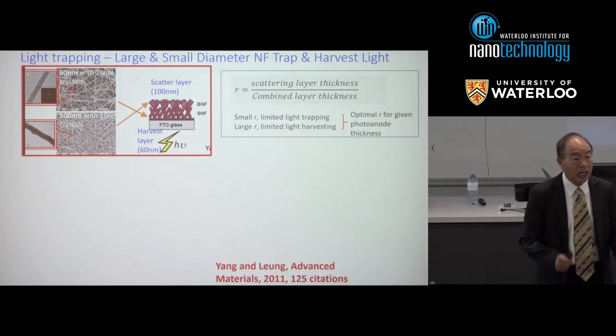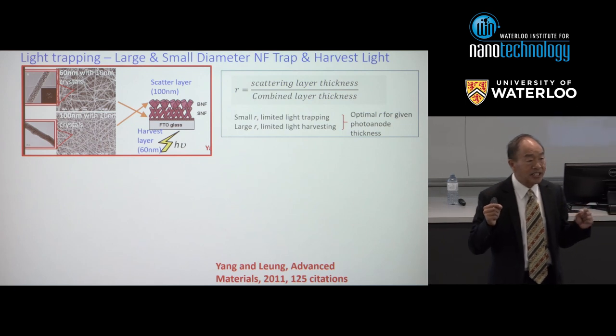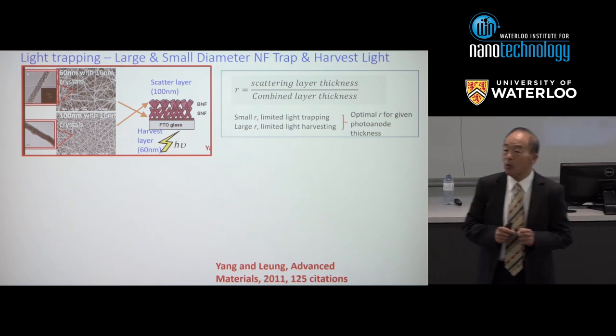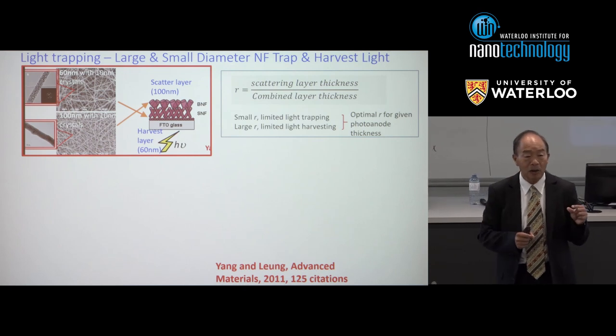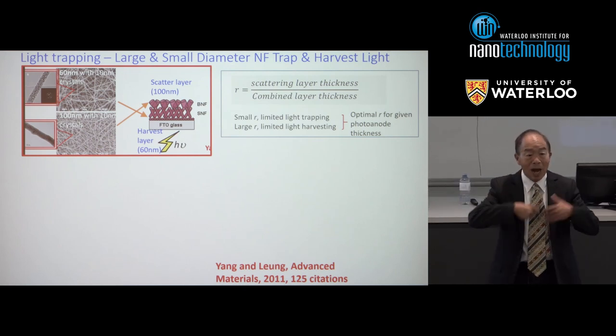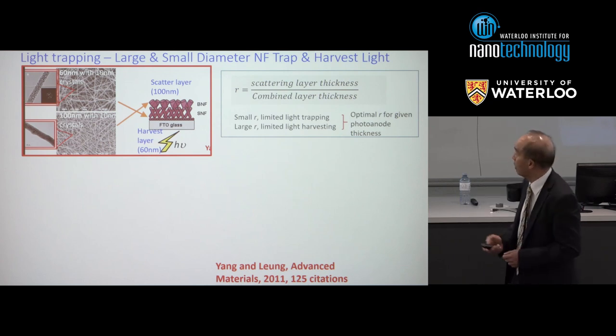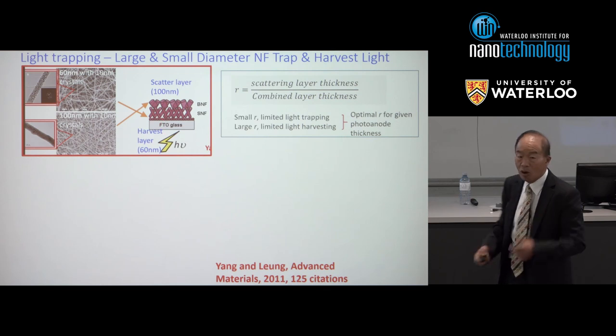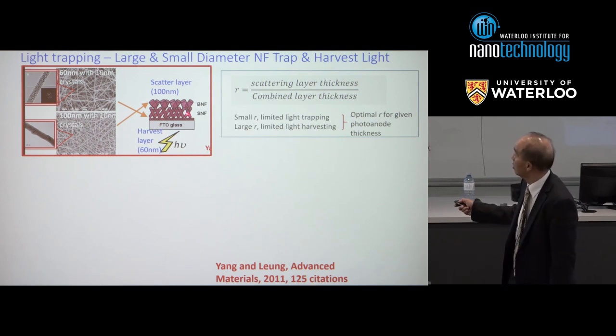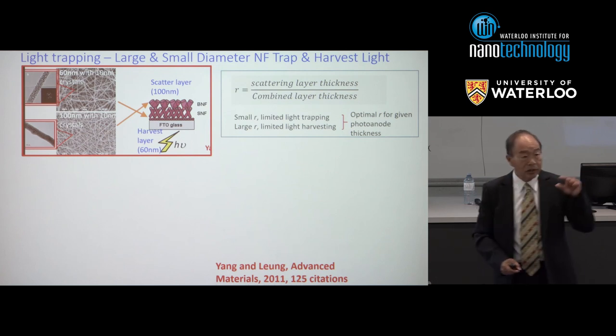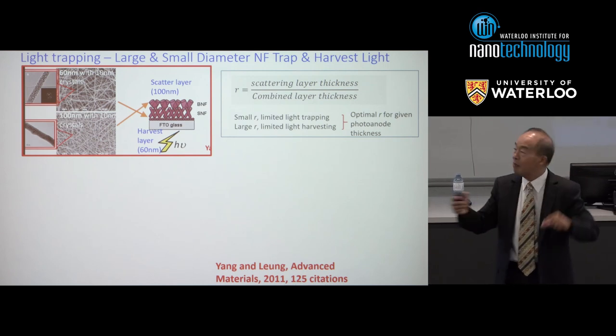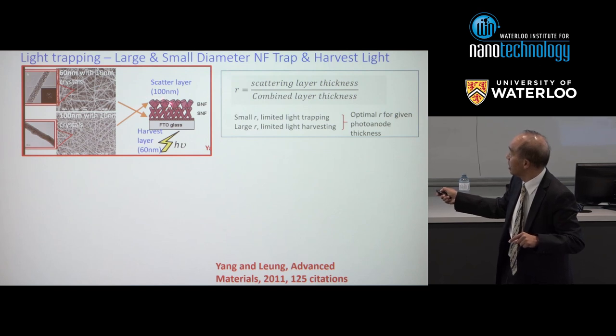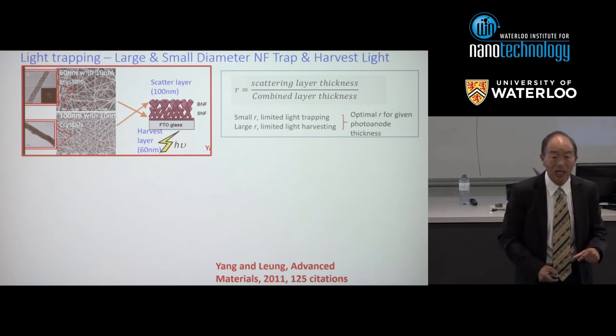The second technology is light trapping. Other than using 60 nm diameter TiO2 nanofibers for light harvesting, we produce a second layer of nanofibers with a larger diameter of about 100 nanometers, so that when light comes in, it bounces around and ultimately gets trapped. An interesting challenge is that if you put too little of this scattering layer, it's not effective; if you put too much, it takes away from the light-harvesting layer. So you have to optimize, which we did using EQE — efficiency at every wavelength.